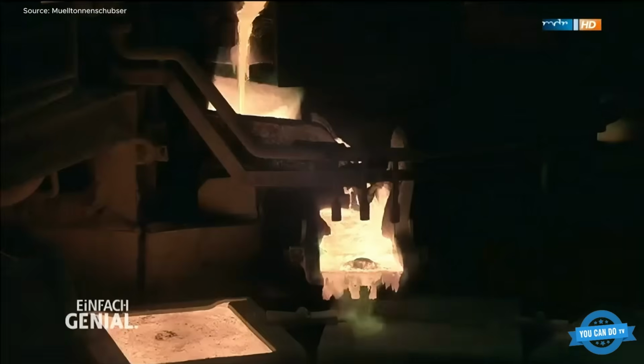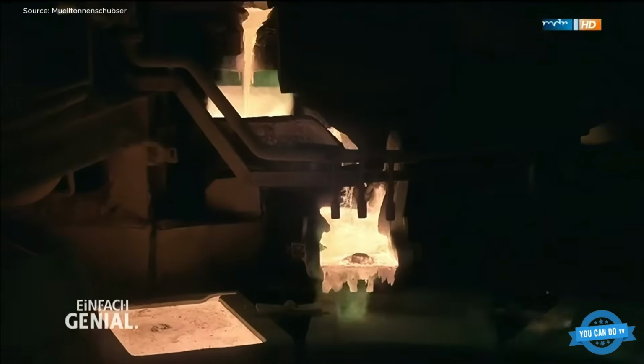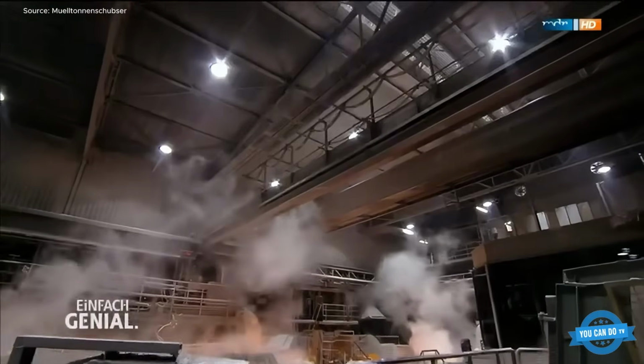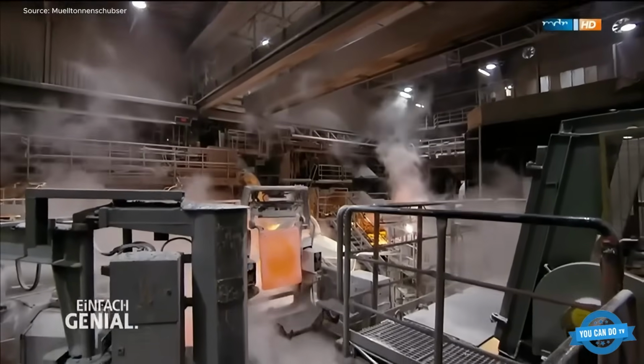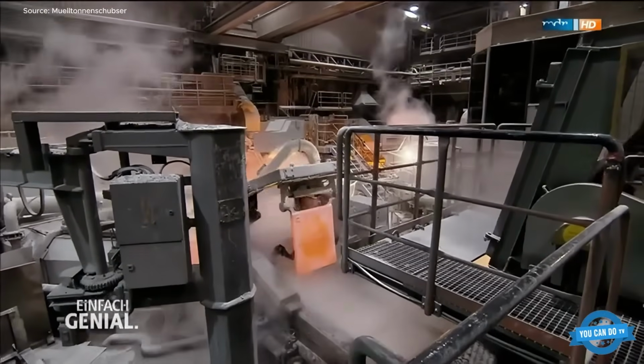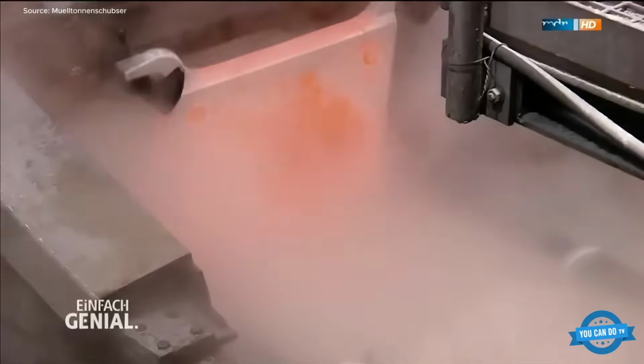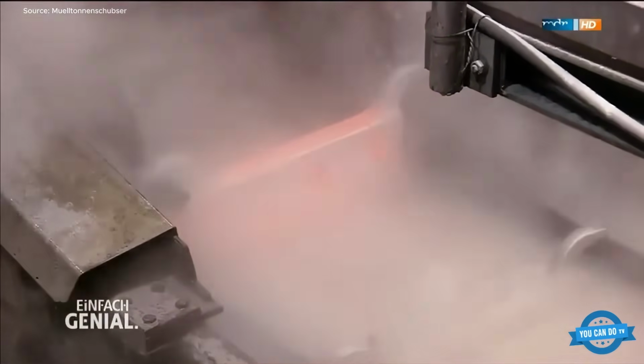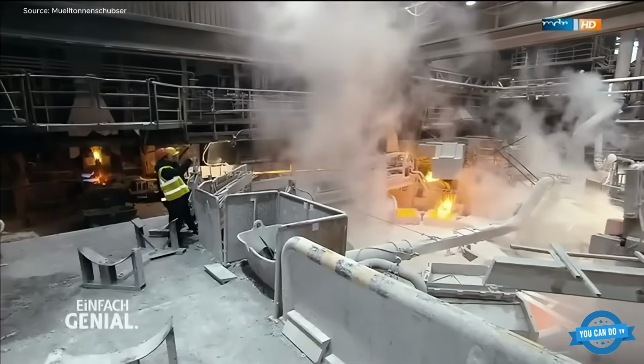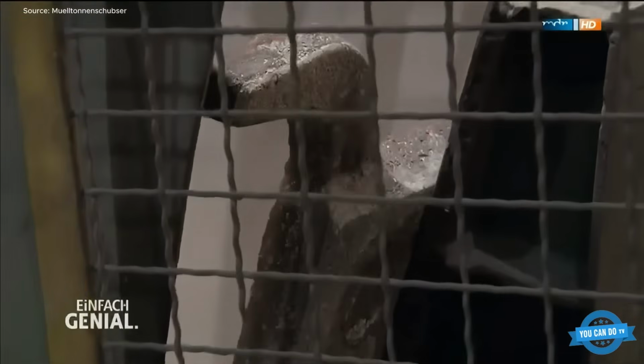To achieve the highest purity, the anodes undergo electrolytic refining. Suspended in acid-filled tanks, the copper is dissolved and redeposited onto stainless steel cathodes using electric current. Over several weeks, ultra-pure copper forms layer by layer. The result is copper with a purity of up to 99.995%.